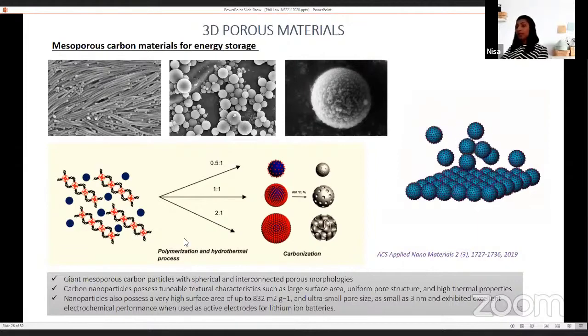So you can see that the pure block polymer exhibits rod-like features, but as the reaction proceeds, the morphology was changing from the thread-like features to spherical-like features. And we use these carbon materials as the electrodes for demonstrating energy storage applications.